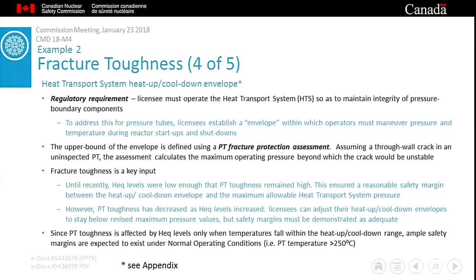I'd like to take a moment to focus on that particular scenario, the heat up and cool down of the reactor. To ensure that they can meet a key CNSC requirement, licensees establish a so-called heat up cool down envelope, which operators must observe as they pressurize and depressurize the heat transport system. To create this envelope, licensees employ a fracture protection assessment, which determines the maximum pressure that a postulated crack could sustain without becoming unstable. So again, I have to emphasize, this is looking at the worst case scenario.